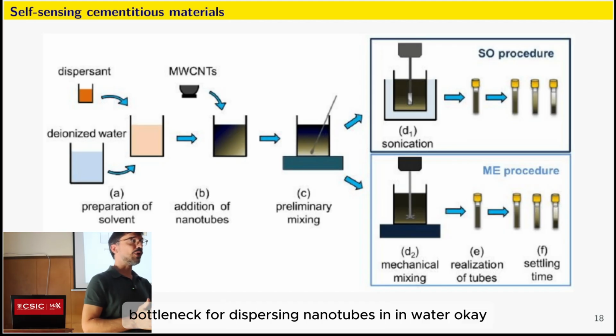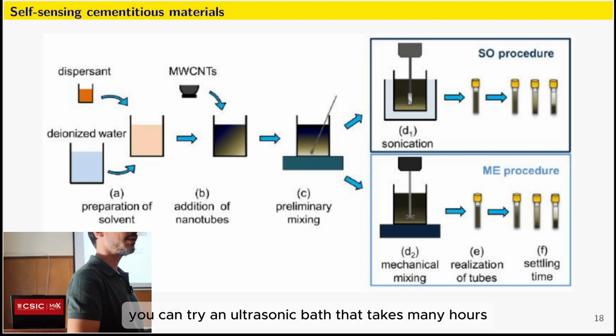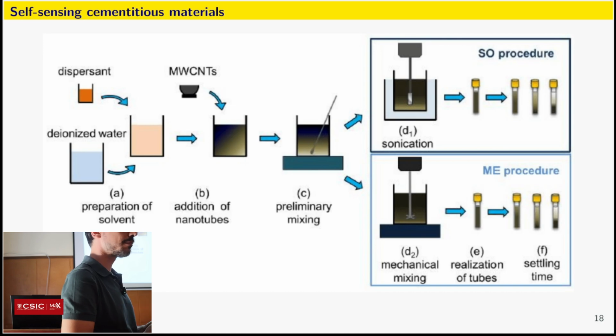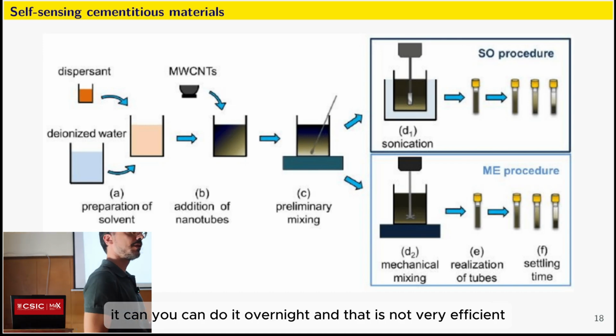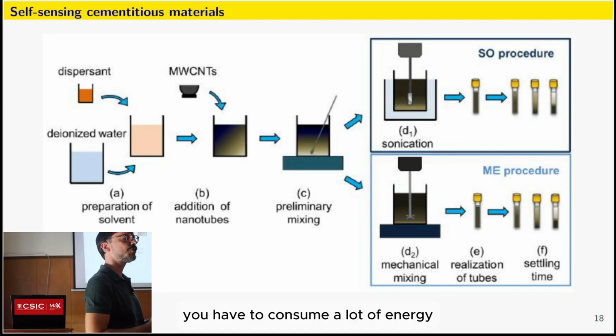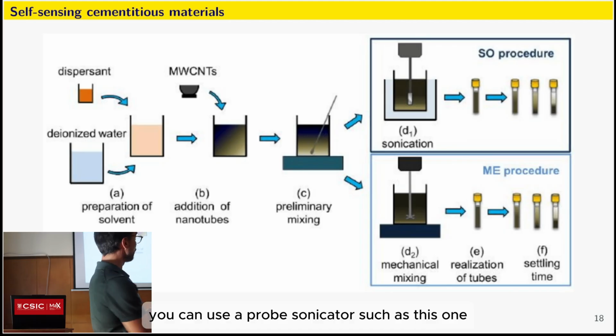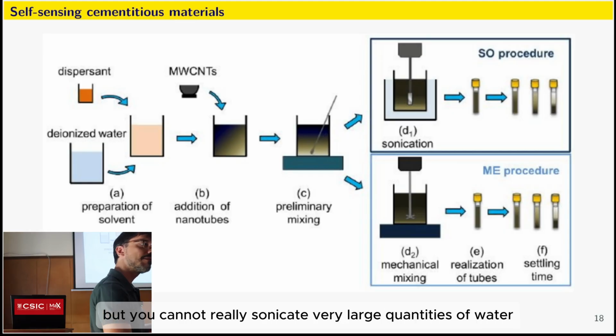Sonication is a huge bottleneck for dispersing nanotubes in water. You can try an ultrasonic bath that takes many hours. You can do it overnight, and that is not very efficient. You have to consume a lot of energy and a lot of time. You can use a probe sonicator such as this one, but you cannot really sonicate very large quantities of water.